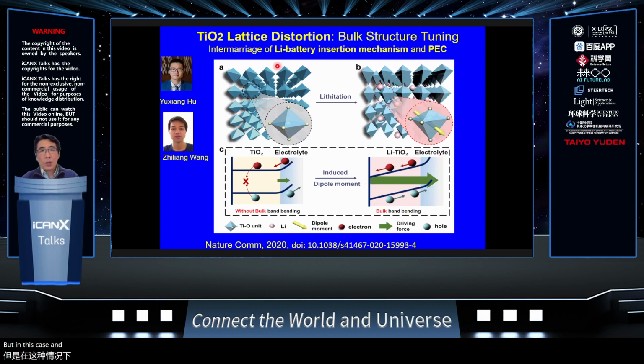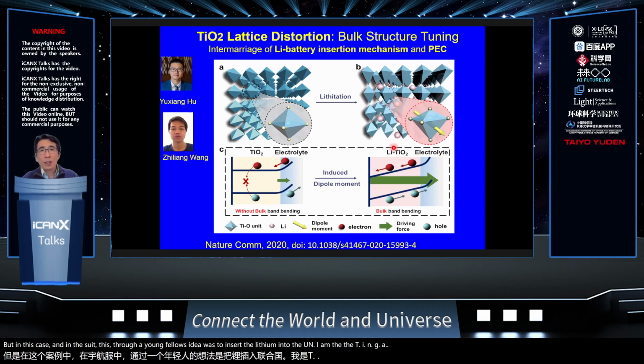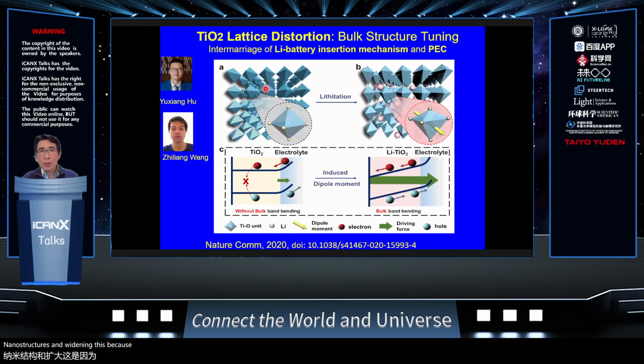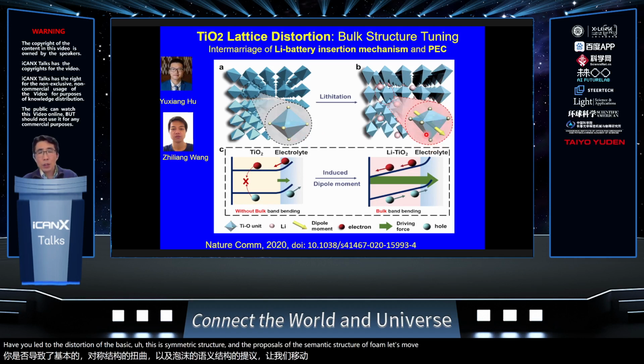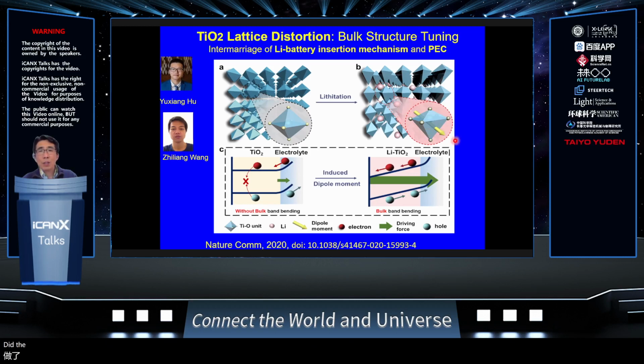But in this case, these two young fellows' idea was to insert the lithium ion into the TiO2 nanostructures. And why do this? Because if you look at TiO2, titanium and oxygen form a very beautiful octahedral structure. But if you insert some species in between, it would lead to distortion of this symmetric structure, and because the structure is no longer symmetric, some dipole will form during this process. This dipole will lead to a built-in electric field in the whole film system.